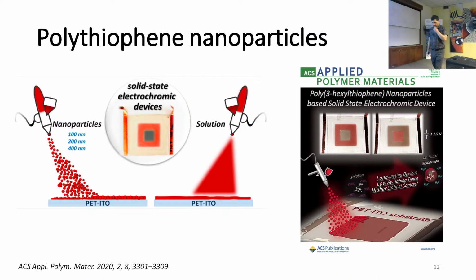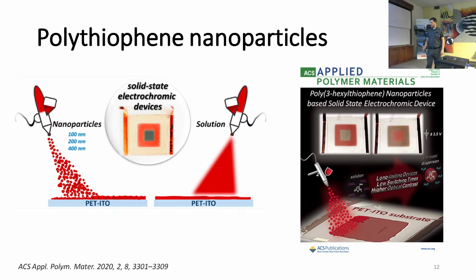What we did was to work with Italian colleagues from Bologna, because we had the technology to make the polythiophene nanoparticles, and these nanoparticles could be produced in water, and so we could deposit this polymer as a water dispersion. This was opposed to the usual technique in which you deposit it in an organic solvent like chloroform. So, in terms of sustainability, it's much better to use water, of course.